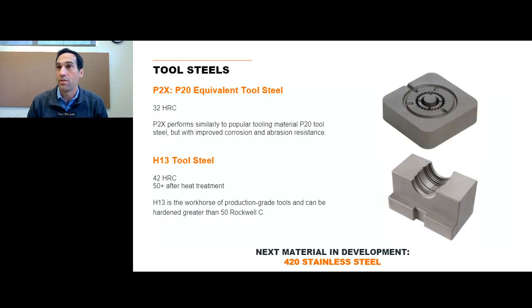So the tool steels, what really matters here is that the tool steels have the properties able to withstand the rigors of an injection molding process or an extrusion process. We've developed two steels already. The first was a P20 steel, which has a hardness of about 32 to 34 Rockwell. Then we also have developed an H13 tool steel, which has a Rockwell of 42 on the C scale and can be heat treated up to the low 50s as a secondary operation. Really, H13, I would say, is the workhorse right now. That's what most folks are using. And we have a new material that's in development and testing right now with partners, which is a 420 stainless steel that we're going to continue to develop this year and release later. So that will continue to expand the breadth of the steels that Mantle will offer.